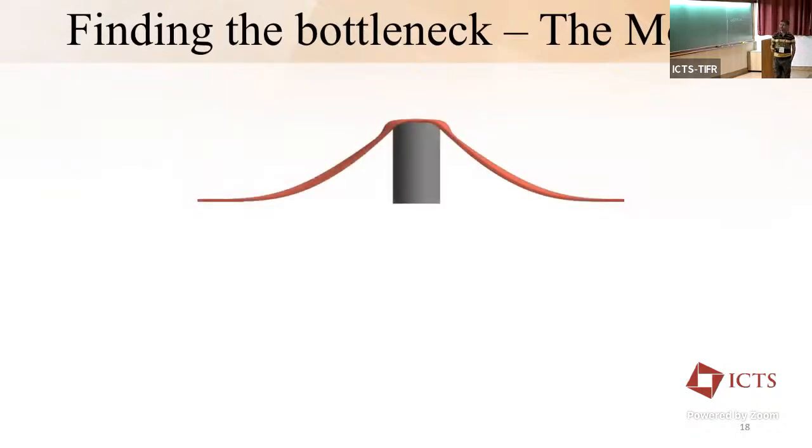So for that, this is an interesting platform where you have these nanopillars, and you put a single monolayer of some material. Here we put tungsten selenide. What really happens is that because you are introducing a strain in this pillar region, there is a band gap reduction in the monolayer. And because of the band gap reduction, if you excite through laser, these excitons will eventually funnel, because this is the lower energy state.